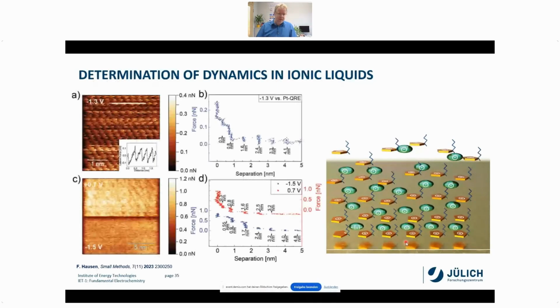And here are examples for that. So in this image B, you see basically when the tip is far away and then is approached. So here from 5 nanometer to the interface, then you see these jumps. And these jumps have the distance of one ionic pair layer. So we can now really count how many layers we have here adjacent to the interface. And here you see a double step. So you see first 0.3 nanometer and then another 0.5.